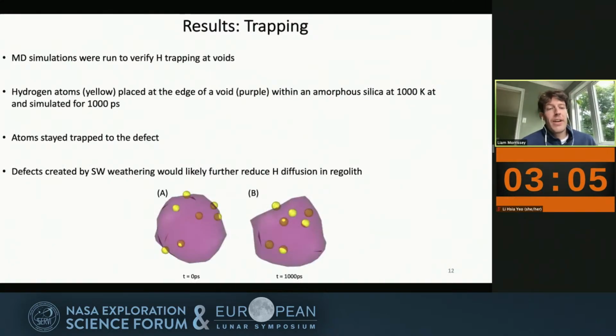At the end here, we ran some MD simulations to verify H trapping at voids, where we took hydrogen atoms in yellow and placed them at the edge of a void in purple within an amorphous silica at a higher temperature. What we found was that the atoms always stayed trapped to the defect, meaning that we demonstrated that diffusion within a defect will be much lower, and that defects created by solar wind weathering would likely further reduce H diffusion in regolith.